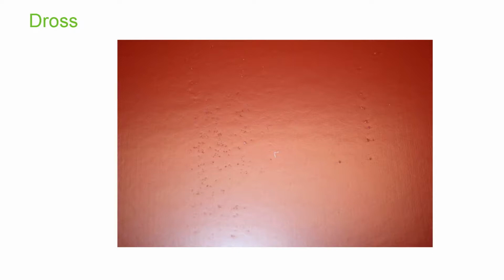As I said, most of the galvanizing lines that supply coil lines are probably automotive capable, at least to GP finish standards. So their dross control procedures should be really very good. But they're not, and you get to see material there. And you can see some clearer spots on that. Not only does that compromise the surface finish that you're looking for, it can also interfere with the corrosion protection that you're looking for by disrupting the zinc layer.